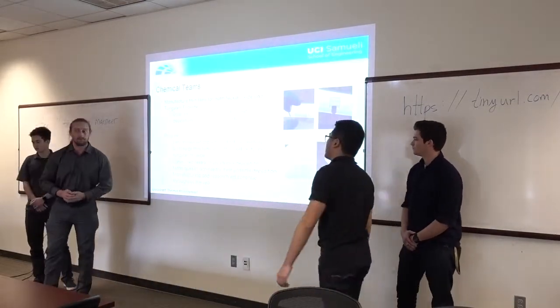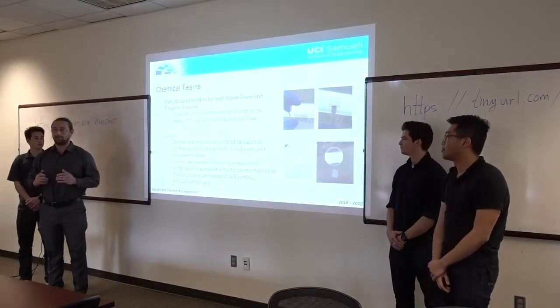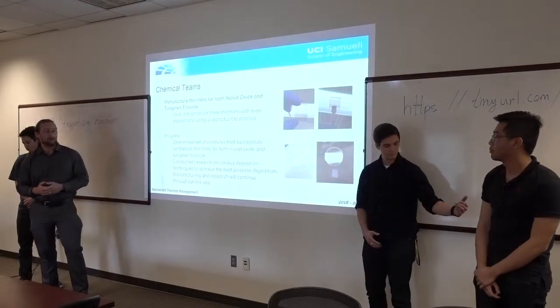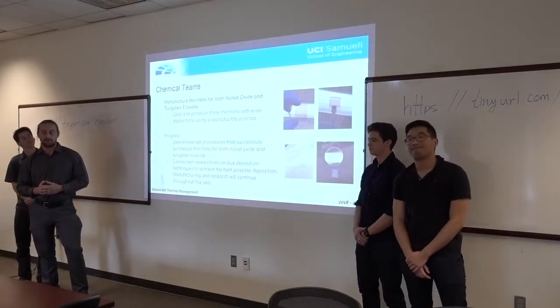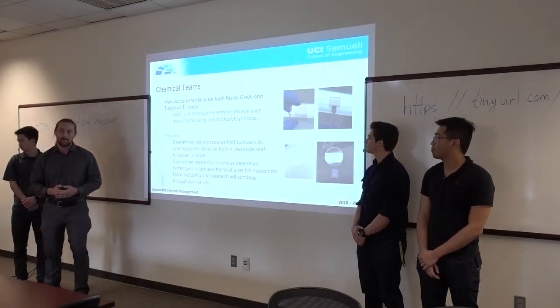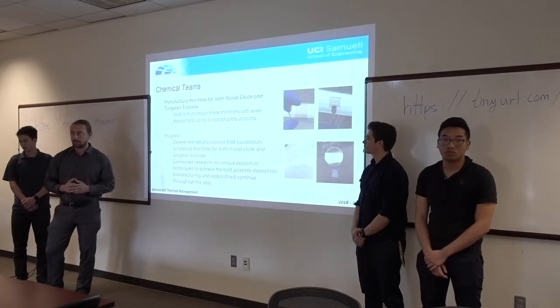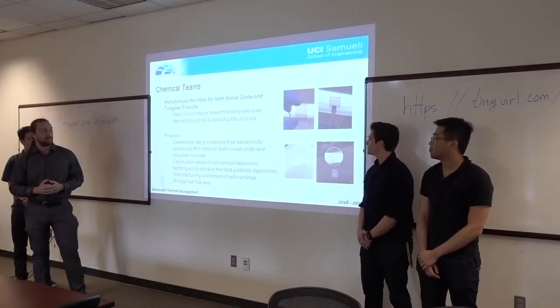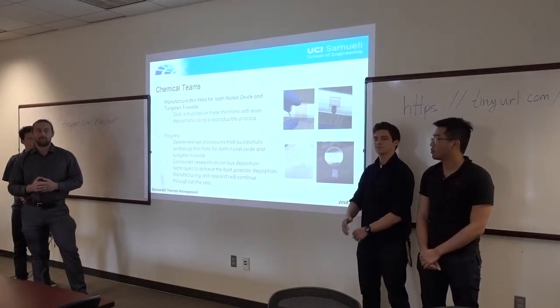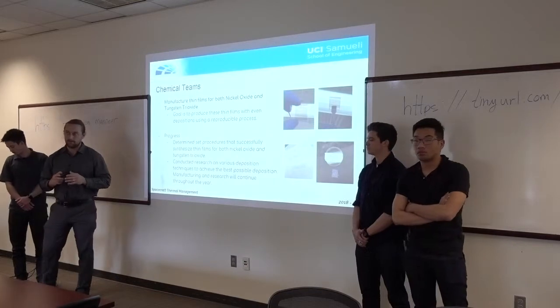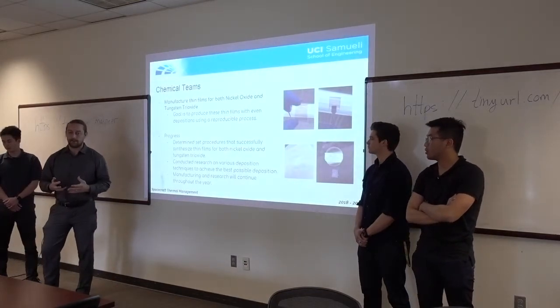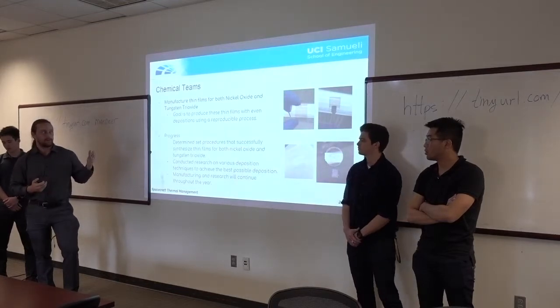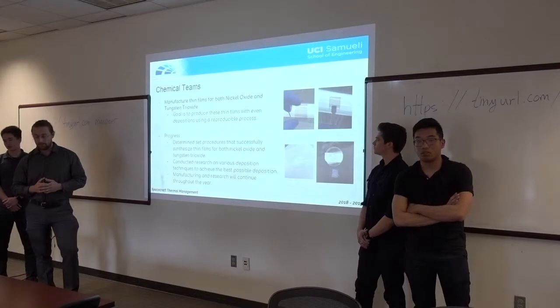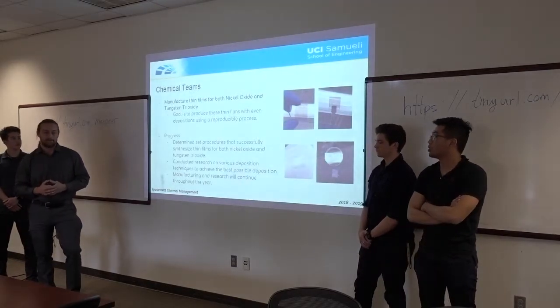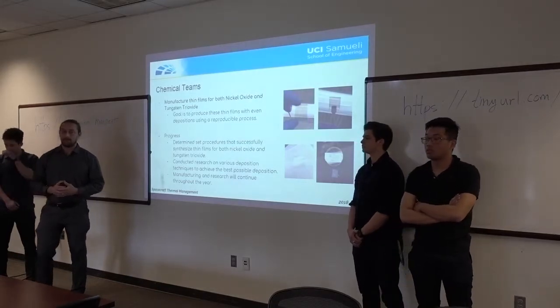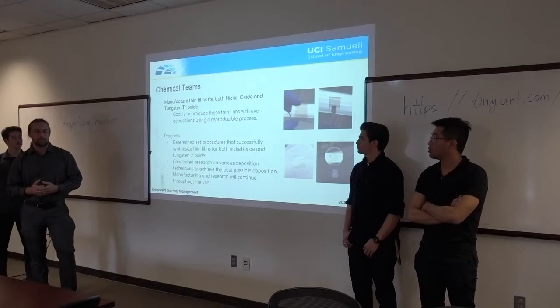So the main goal of our team was to achieve a fine deposition of nickel oxide and tungsten onto FTO and ITO slides. The three main steps were to first clean the slides with the RCA clean, which involved submerging the slides in hydrogen peroxide, getting rid of all the impurities on the surface. Followed by chemical bath deposition, where we submerged the slides on wires into the solution in the beaker and waited for our chemicals to react and for the desired either nickel oxide or tungsten to precipitate onto our slides. After this, we would take out the slides, rinse them with deionized water, and anneal them to get rid of all the moisture from within the material.